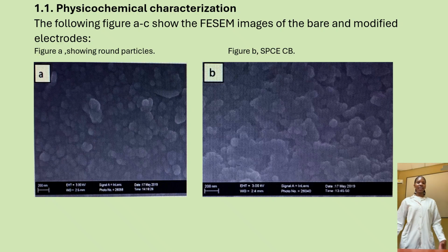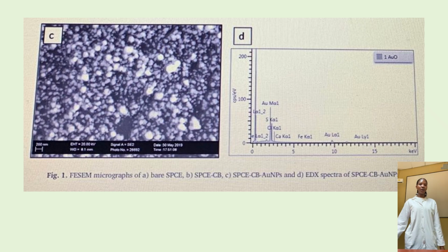Under results and discussion, we first have physicochemical characterization, which shows the FESEM images of the bare and modified electrodes. The round-shaped particles shown in figures A and B are similar, which suggests that the carbon ink in the SPCE and the synthesized carbon black have similar structures. However, figure B shows more porous holes compared to A, likely due to the extra layer of carbon black that was added. Figure C shows small bright round spots.